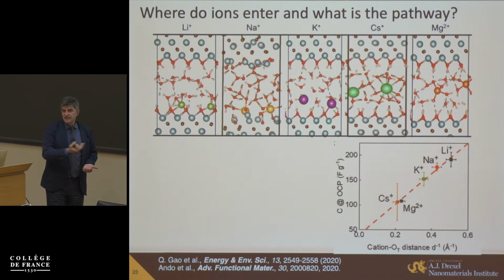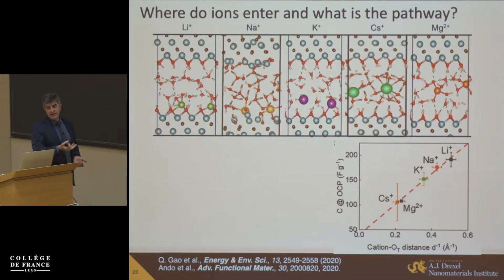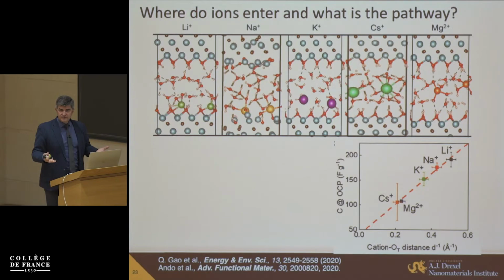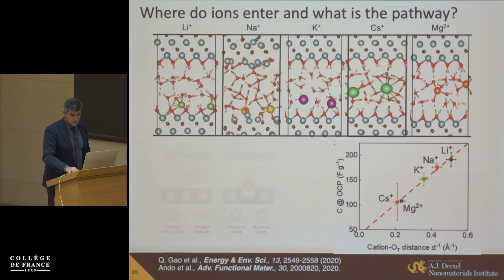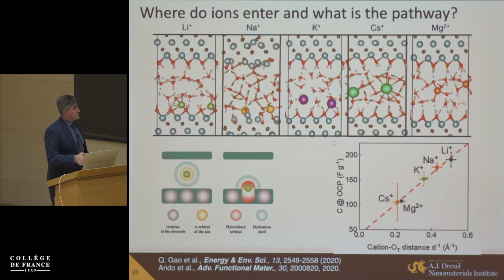You pull some of the electron density towards these ions. The closer the ion in, even at the same single charge, you basically have stronger polarization of the titanium atoms here. So this is kind of a schematic from simulation showing what happened. This ion, say, sitting in the middle, far away, has little effect here, and the closely coming lithium and sodium interact much stronger, and there is stronger polarization here.